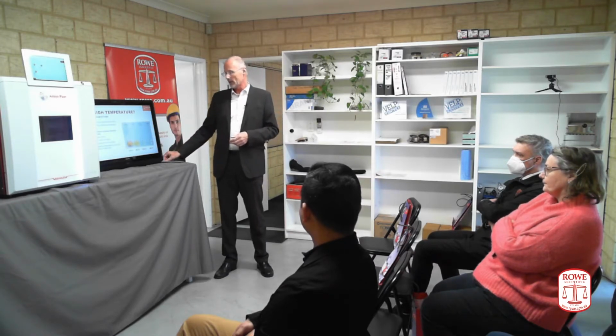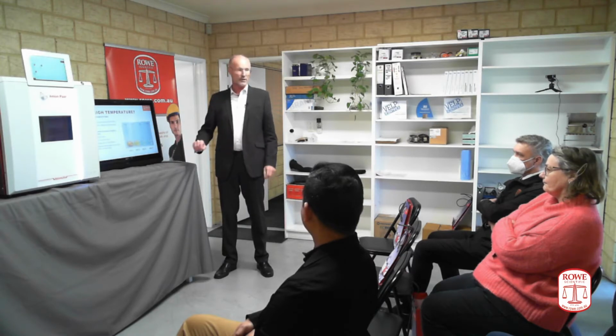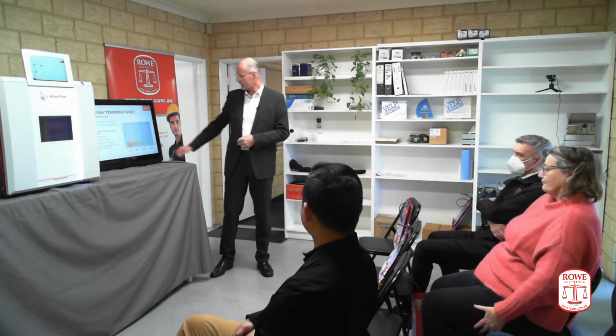on the ICP. The more carbon you introduce to your ICP, the more soot deposits you will have on the torches in the torch compartments, the more cleaning efforts you need to apply, and the more measurement interferences you may have depending on what kind of alloys you're looking for. And this may be less critical for ICP optical emission analysis, but ICP MS is particularly sensitive to residual carbon that may form cluster ions in the quadrupole analyzer.